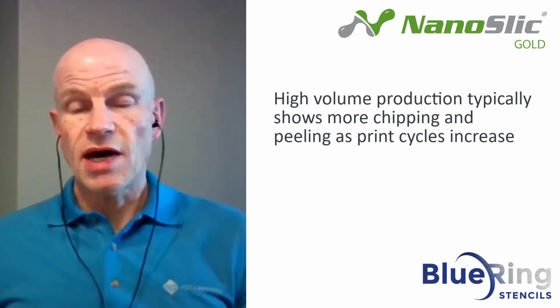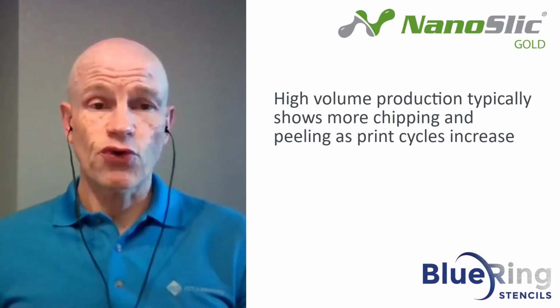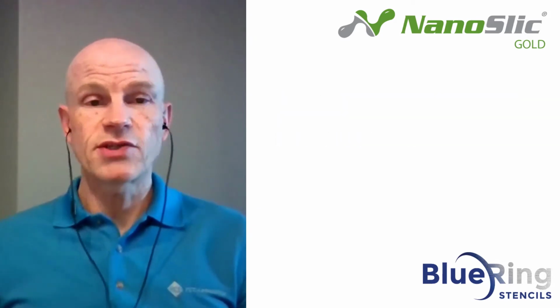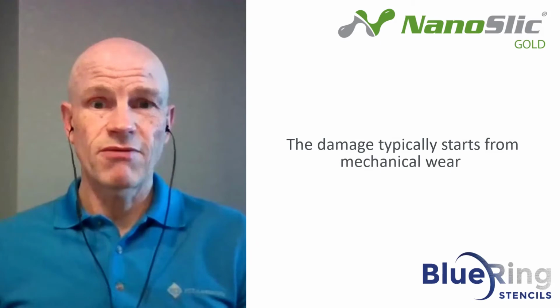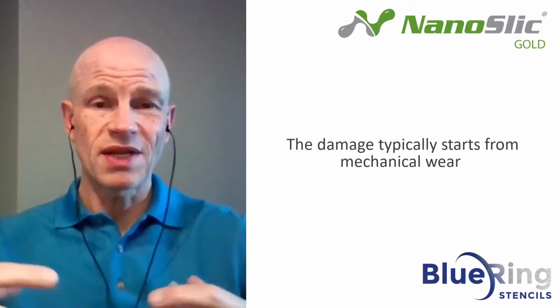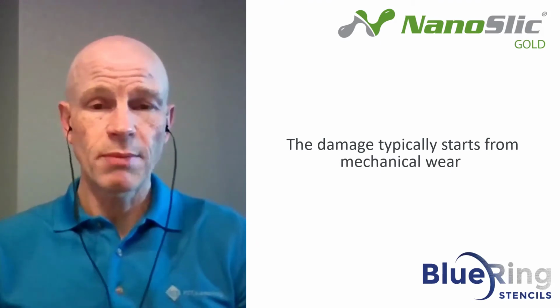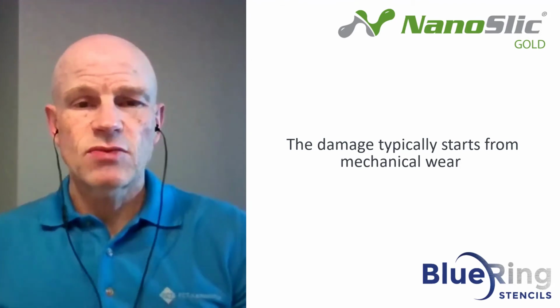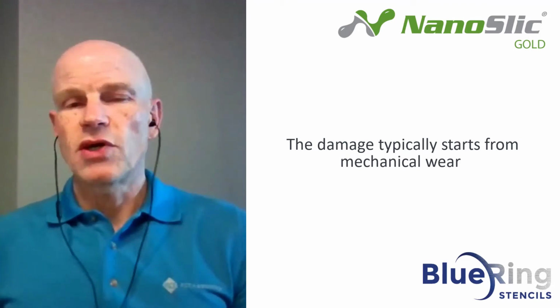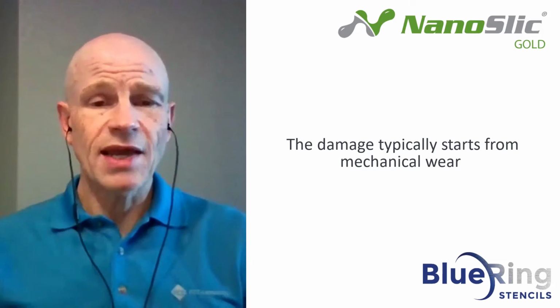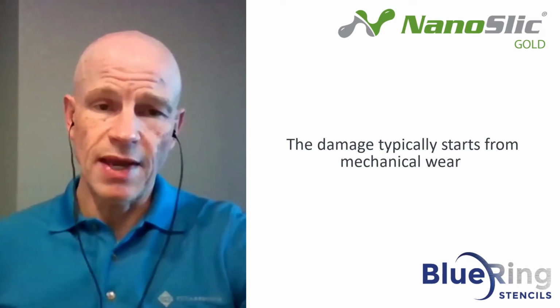You can actually see the high spots of the circuit board eventually get translated up into the steel of the stencil itself. The pressure is great enough over a period of time that the steel gets deformed and bent permanently with the circuit board image. And so that's really where the damage begins with the coating. It's a mechanical type of damage, not a chemical damage.